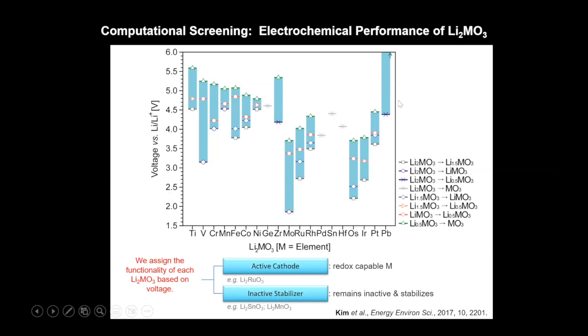And from this kind of calculation, we can classify materials as either possessing voltages in a range that's accessible via today's electrolytes, in which case we would call this material an active cathode material, capable of doing redox. Or in some cases, we find that the voltage is at very high voltage, or mostly at high voltage, in which case the capacity is probably inaccessible, but the material can still act as an inactive stabilizer of the layered structure.